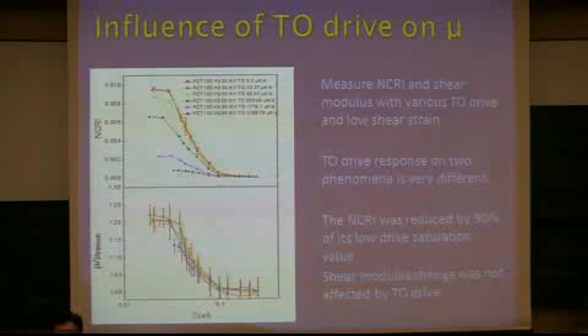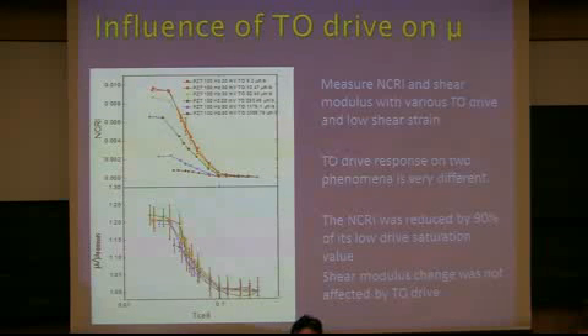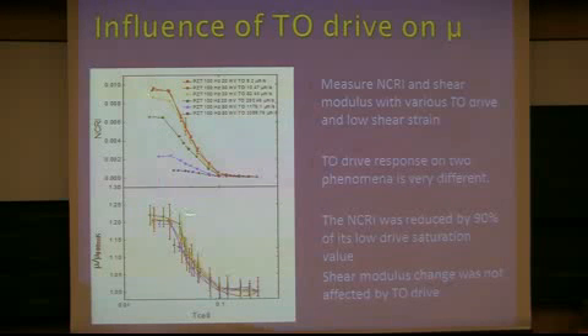If both phenomena, the shear modulus change and torsional oscillator response, come from the same microscopic origin, what's going to happen? If you change one of the properties, then you expect the same change in the other property, right? This is the same cell, simultaneous measurement. As I told you, using AC oscillation velocity, you can suppress non-classical rotational inertia. Here, we suppress almost 90% of that. Then we measure, at the same time, the shear modulus. No change. Interesting, or maybe obvious from the DC rotation experiment.